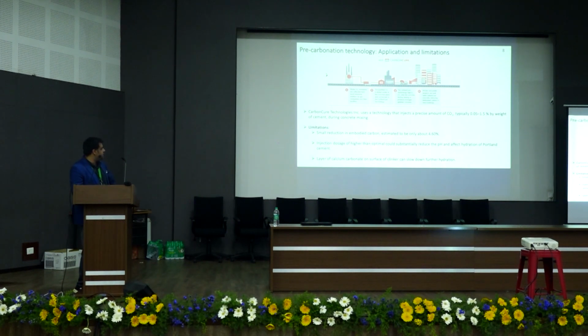And there are some drawbacks as well. So, besides a very small reduction in embodied carbon, you can also acidify the water. The pH can drop, and that can lead to other problems, for example, retarded hydration at later stage. The second problem is that when calcium carbonate is formed, it forms as a coating on the surface of the hydrating grains, and that can stop or retard hydration at later ages. So you have to keep on curing your concrete for longer time, for better strength gain.